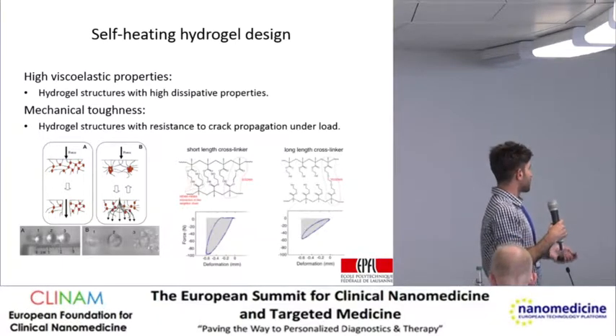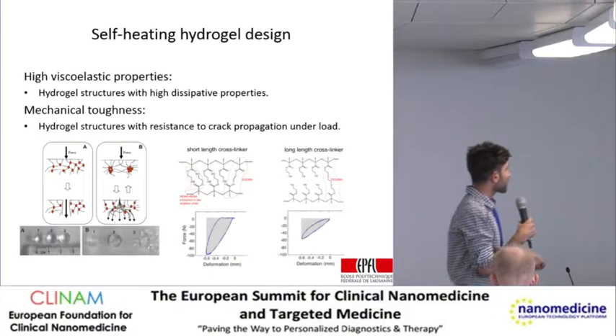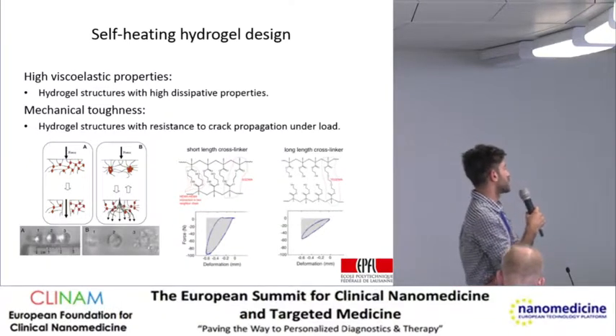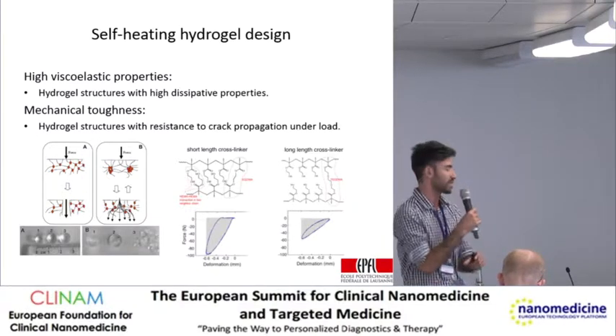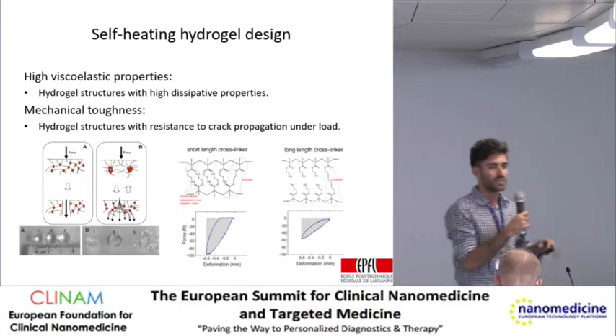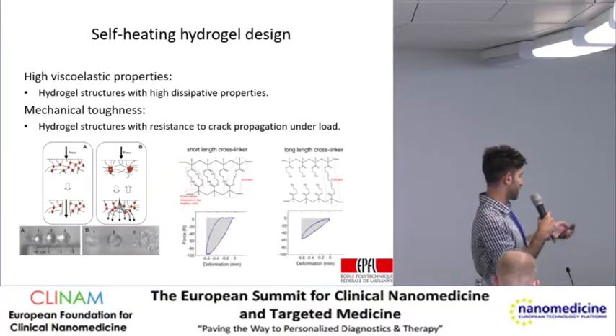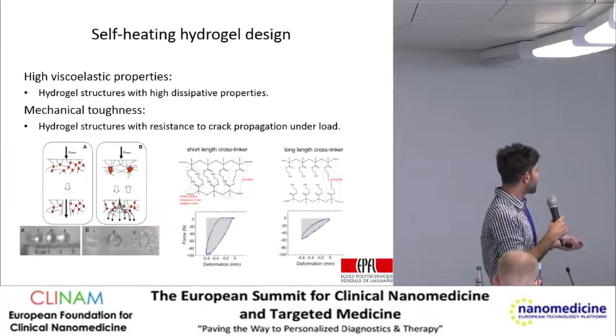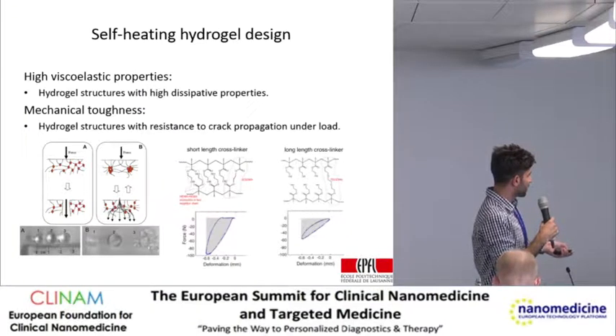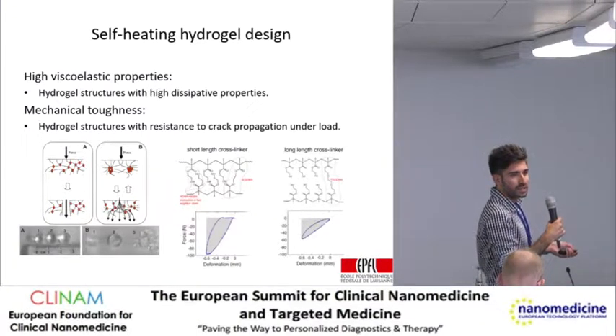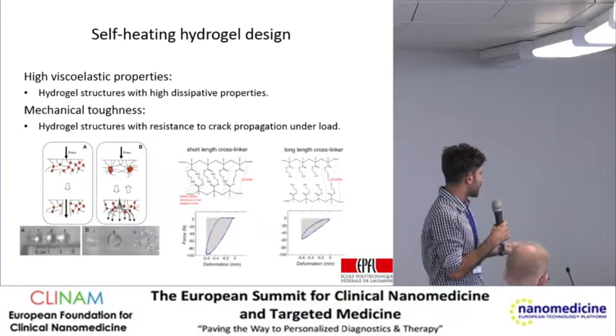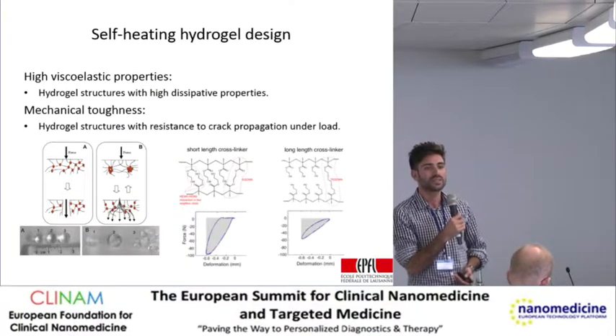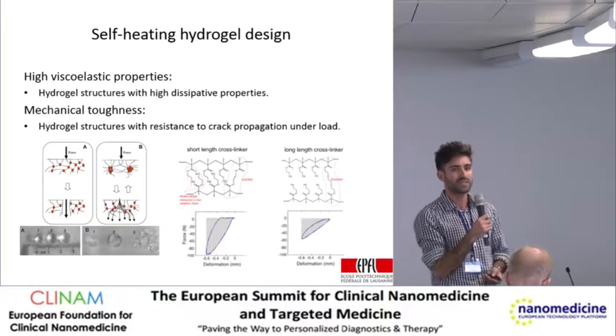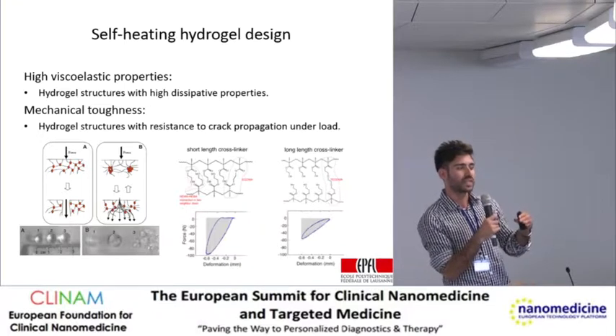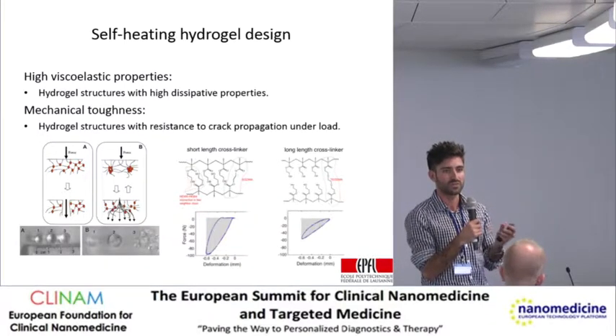Studying different hydrogel structures, we found that HEMA-based hydrogels, hydroxyethyl methacrylate hydrogels, have good properties. When you use them with a very small, short-length crosslinker like HDMA, they can produce lots of friction inside the material when you apply load, and they dissipate lots of energy. The hysteresis curve, which is like an identity for dissipation under load, for this hydrogel with a very short crosslinker is much higher than with a long crosslinker. And dissipation is a good thing because it favors the mechanical toughness of the gel. When you have a gel with high dissipation, it dissipates the input work and doesn't let the energy be stored in the material and lead to cracks.